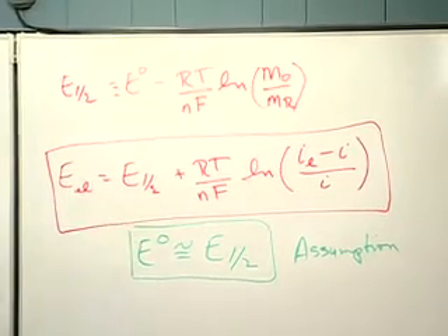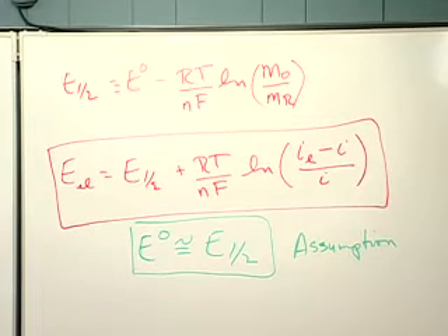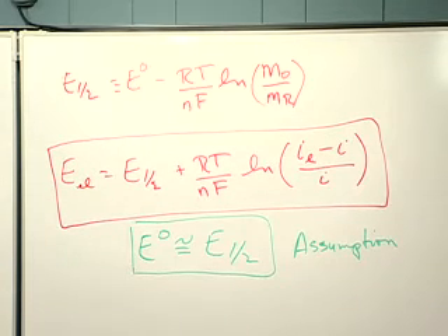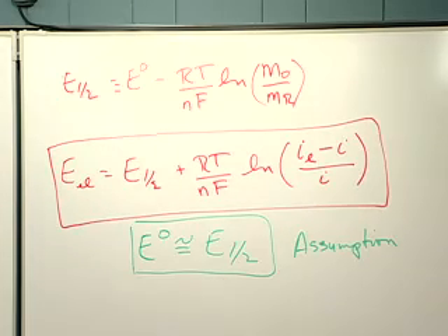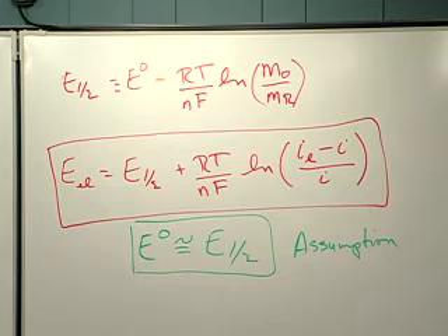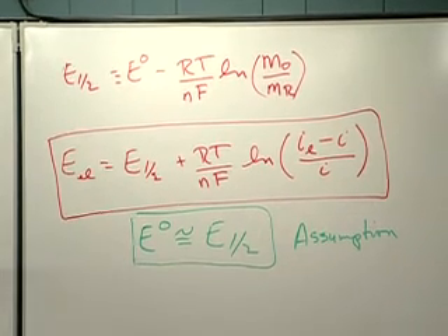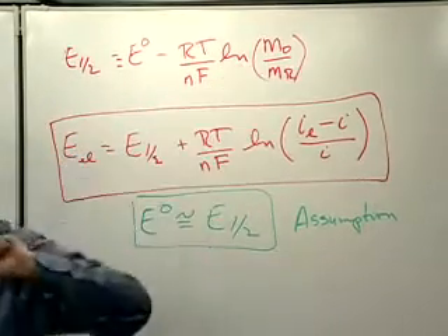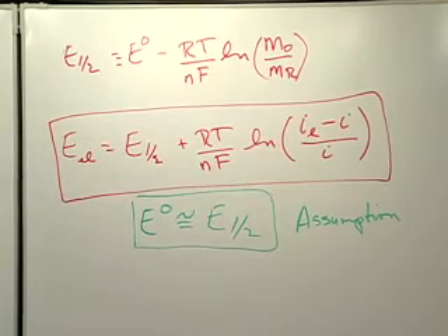I mean, at the point that you make a measurement and say, oh, the oxidized species has a different diffusion coefficient than the reduced species, it has a very different diffusion coefficient. So a diffusion coefficient difference of 10% is really not measurable, even on a good day. And it's got to be more on the order of magnitude difference before you get that. And of course, an order of magnitude does start to have an impact then on a log term. But that's what it takes.